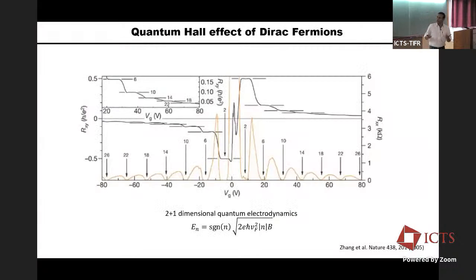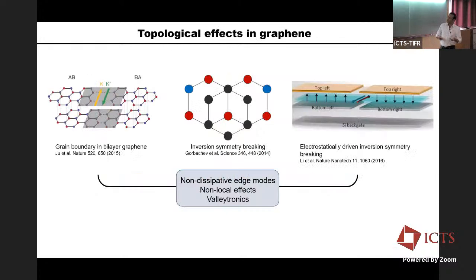Of course, in addition, we must not undermine the application of graphene in fundamentals. A little bit was said at the beginning. Graphene's entry was immediately associated with this new type of Hall effect, which came in through two-dimensional Dirac fermions, and led to a very distinct set of Landau levels, which has now become like an iconic example of quantum Hall systems in graphene Dirac fermions. Then after the quantum Hall effect, we started topological effects in graphene. For example, one of the major directions in graphene is to create grain boundaries. For example, the grain boundaries could be in bilayer graphene.